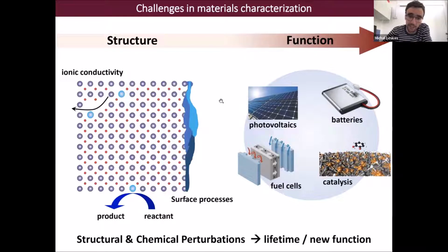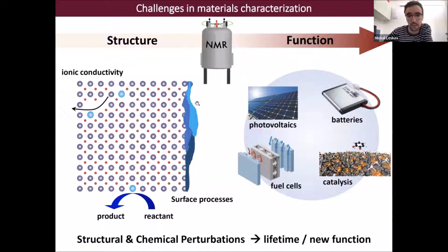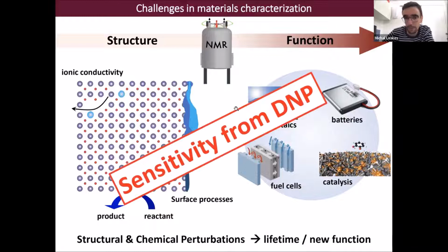And you can imagine that NMR is an ideal tool to do this, as it can give us information on the local atomic scale. However, if these perturbations are scarce and rare in the material, we suffer a lot from low sensitivity, to the point that sometimes we cannot even detect them with NMR. So our group has been focusing on introducing the DNP methodology to increase the sensitivity and ultimately gain information about the structure of these materials.